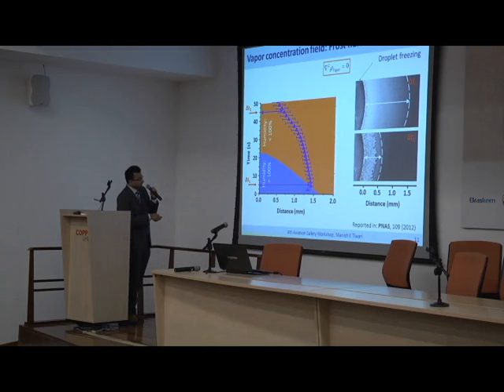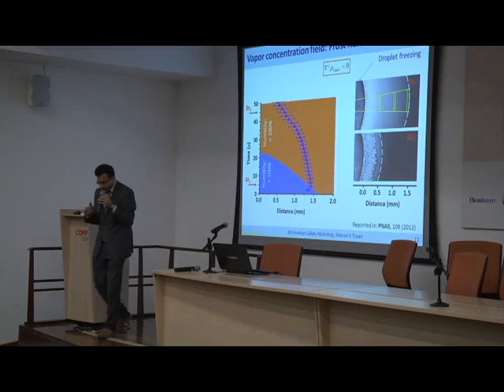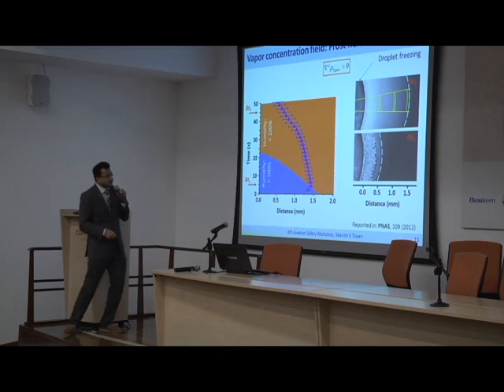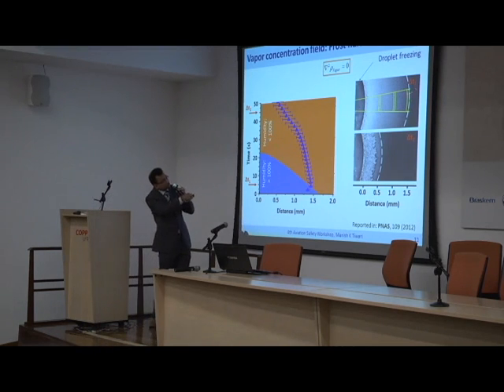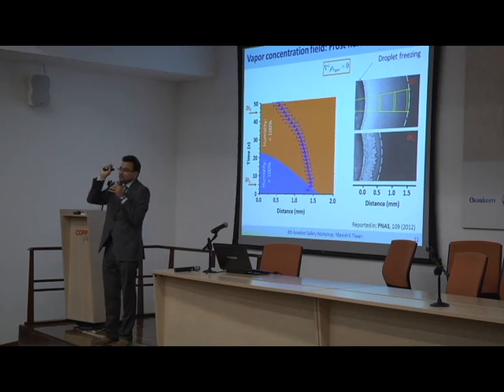So these are experiments which show that I have a sudden condensate ring formation, and some of it actually can evaporate, giving me a final frozen ring that is somewhat extended from the original droplet here. And if I'm doing all of this correctly, I should be able to correlate that with the size of the so-called condensate droplets as well. What did we do for that? Indirect measurement. So we took these high-speed camera images, and we broke them down into three sectors, and we simply measured the brightness of these images, which more or less corresponds well to the size of the tiny condensate drops we are forming.